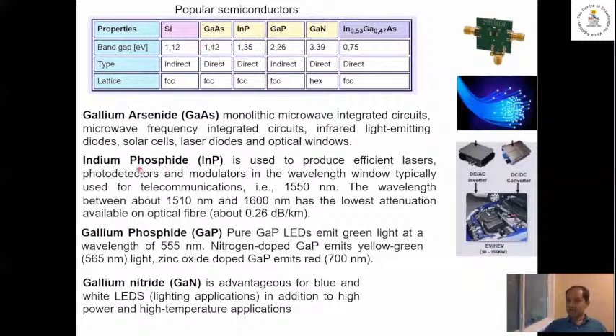Then there's indium phosphide, with a band gap of 1.35 electron volts. And this material is good because it can be used to produce lasers, detectors, and modulators at a wavelength of 1550 nanometers. This is an important wavelength because these days we use optical fibers for communications, and optical fibers are most efficient at this wavelength. And so indium phosphide complements optical fibers.